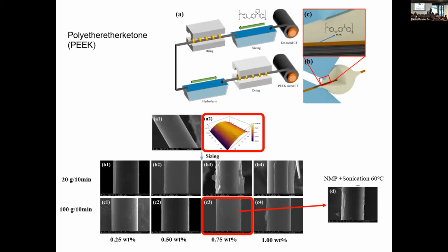So first, we know the matrix is PEEK, and the process is thermal treatment, the surface treatment called fiber sizing. For carbon fibers, one function of the sizing is to create the interfacial bonding between the fiber and the matrix. So we know the matrix is going to be PEEK. If the sizing agent is also PEEK, that will certainly be good.